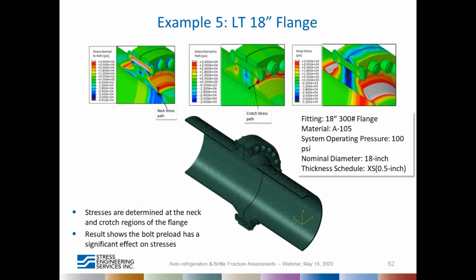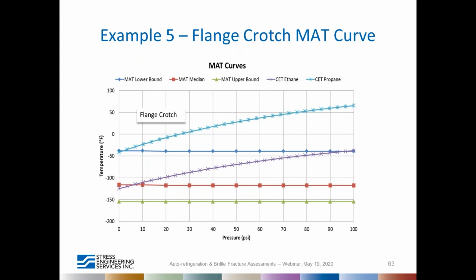Now, there's one other issue that I mentioned earlier regarding the Beringen, Belgium plant flange failure that resulted in a lot of discussions across the industry about the forged flanges, the A105, for example, about their quality and usability. There's a lot of studies out there. This one example is where one particular low toughness flange was being subjected to bolt preload and operational loads stemming from CAESAR or piping stress-based analysis, and looked at the MAT curve based on the data available from Charpy tests across the board. And the MAT curves were developed using pure fracture mechanics approach for various fracture toughnesses. So there's a lower bound, a median and upper bound, depending on the data available.